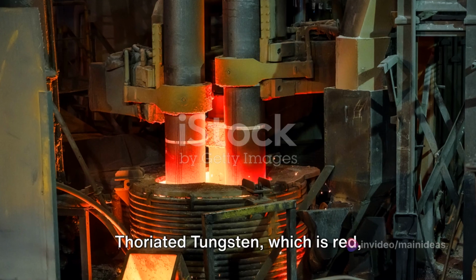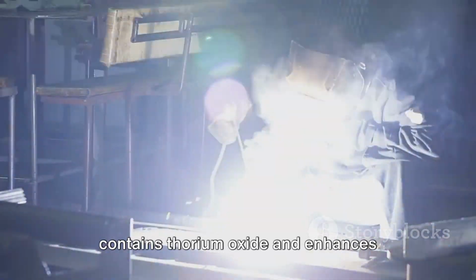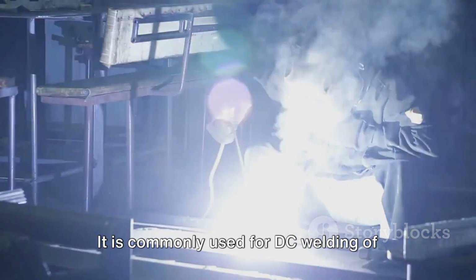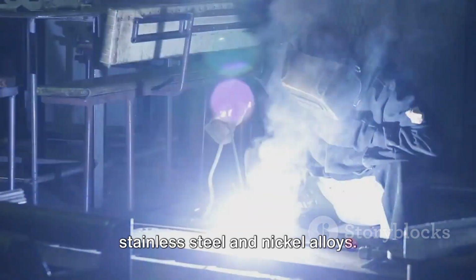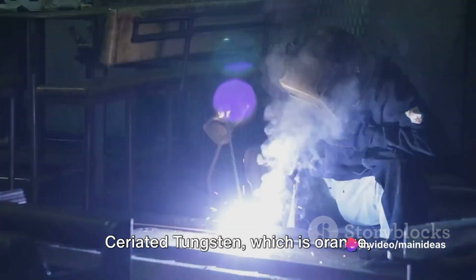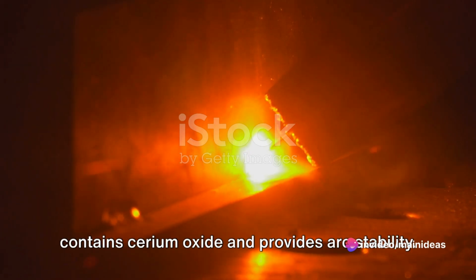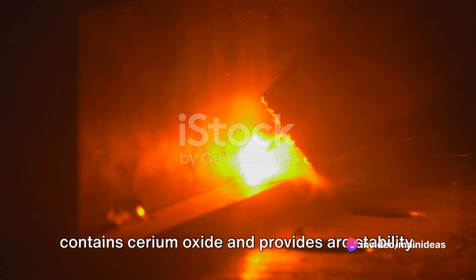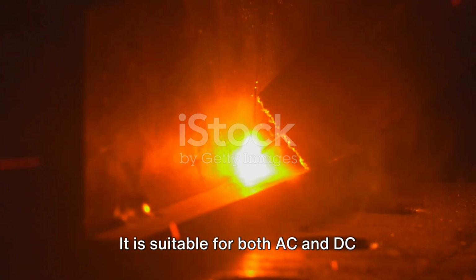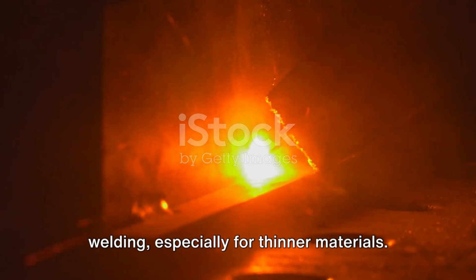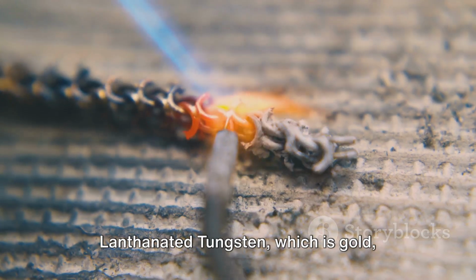Thoriated tungsten, which is red, contains thorium oxide and enhances electron emission. It is commonly used for DC welding of stainless steel and nickel alloys. Ceriated tungsten, which is orange, contains cerium oxide and provides arc stability. It is suitable for both AC and DC welding, especially for thinner materials.